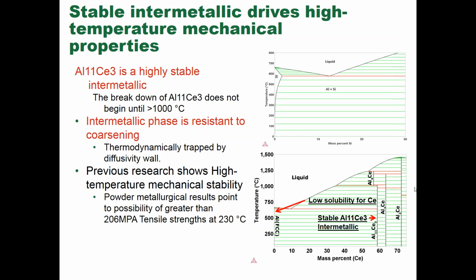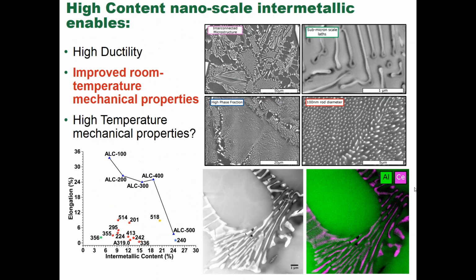And what we're really trying to say is that cerium has no real solubility in the aluminum phase, and so it's got nowhere to go, and so it's thermodynamically trapped. The original research was in powder metallurgy, and the powder metallurgical results point to a possibility of fairly high tensile strengths up to about 230 degrees C. So it seemed like a possible application for a cast alloy.